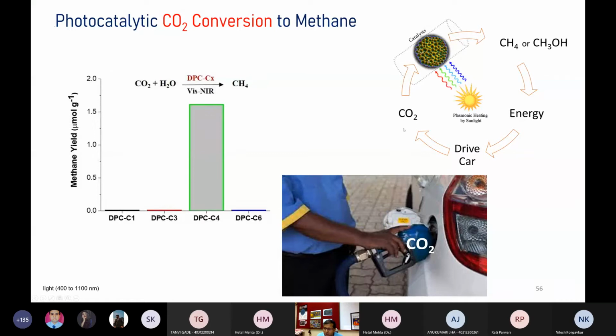And once you burn methane, you get CO2 back. And don't let that CO2 go into the environment, but circulate it back to the catalytic reactor, right? And then again get the methane. You see a cyclic economy, cyclic carbon cycle, where ideally once you fill the CO2, you will never have to fill the fuel again. So if this is feasible, you can see the reaction is possible. CO2 to methane is possible, but obviously this needs to be done at a dramatically greater efficiency, in kinetics and productivity, and this is where the science is lacking, and this is where the fundamental research is needed, where I can really develop a catalyst which is good in light harvesting, which is extremely fast in converting CO2 to methane, and which converts a large amount of CO2 into methane.